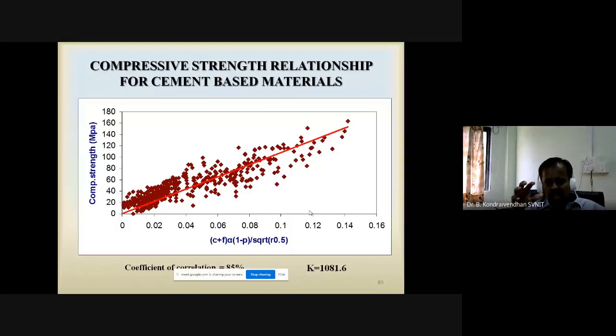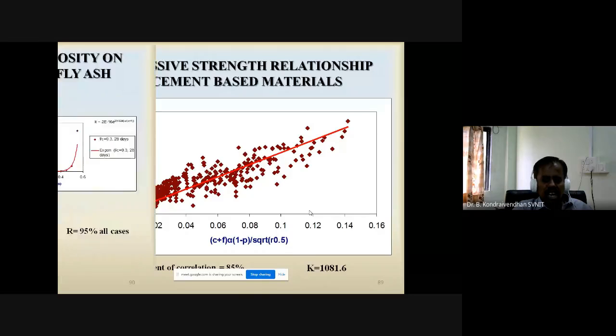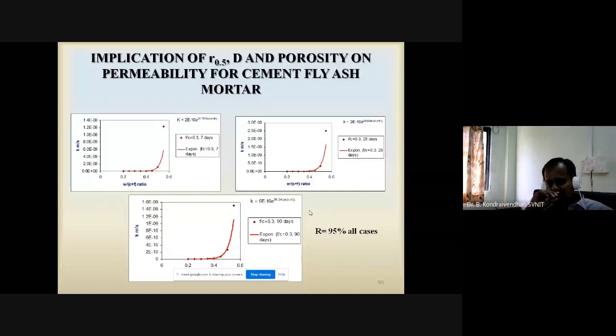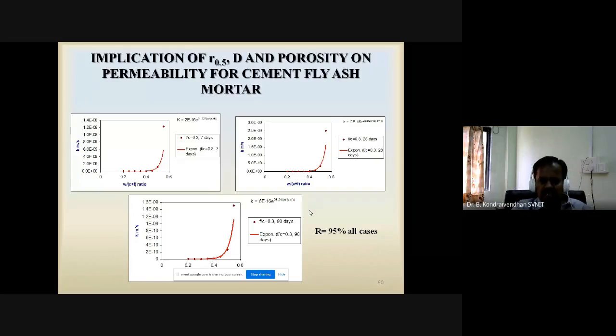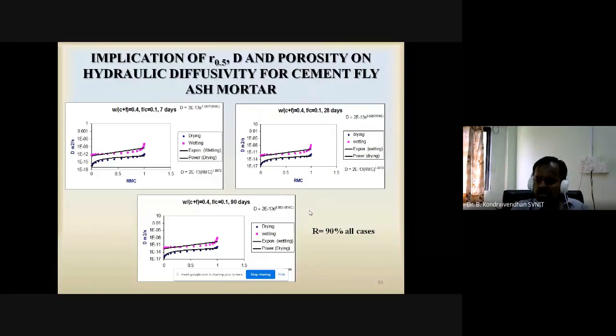Okay, and we put all the data together, and we got one common relationship for the cement-based material. In that case we got a K of 1081.6. That kind of exercise we have done, and we also extended this work to the permeability and hydraulic diffusivity. In the case of permeability also we got a similar trend. The permeability versus water-binder ratio is also showing the same trend that was predicted by T.C. Powers in the year 1960 for different water-binder ratios. This work has been extended to the hydraulic diffusivity, and there also we have done it for both wetting and drying cycles, and the hydraulic diffusivity versus relative moisture content has been given in the graph. Here also, if you look at the equation, it matches the equation given by Hall et al. for the hydraulic diffusivity.